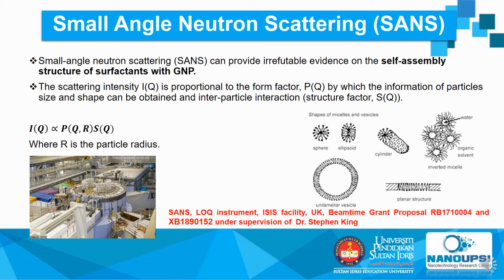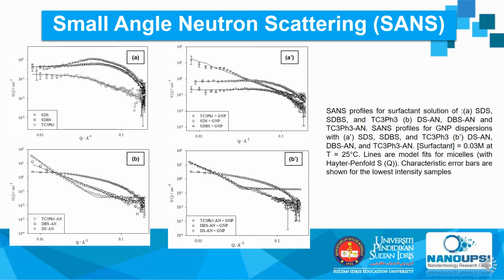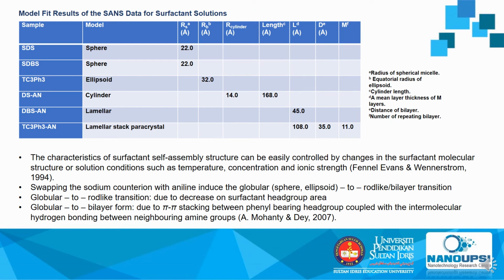So for the last characterization, in order to study the shape and size of the micelles, we did small angle neutron scattering measurements. This was carried out at the LOQ instrument in Rutherford Appleton Laboratory under the supervision of Dr. Stephen King. All the data were fitted in the following tables. As we can see in the table, the characteristics of self-assembly of the surfactant can easily be controlled by changes in surfactant molecular structures. And as you see in the table, swapping the sodium counter ion for aniline groups changes the globular structures of SDS, SDBS, and TC3PH3 to rod-like or bilayer transitions.